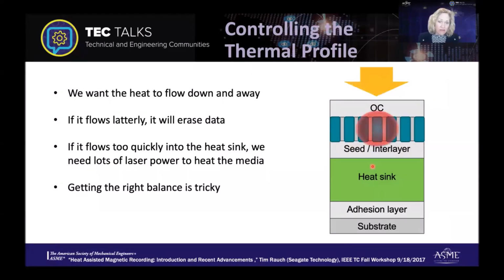So when we have that near field interacting with the media and creating the small heated spot, we want that spot to get heated quickly and then be able to have that heat flow down and away so that by the time the disk rotates around again, the spot is no longer hot. Otherwise, the write field will write over it again and erase it. So we want to be able to get that cooled quickly within a revolution, but not so quickly that you have to keep dumping more and more laser power in. So that balance is important.